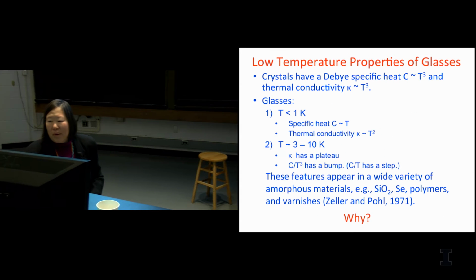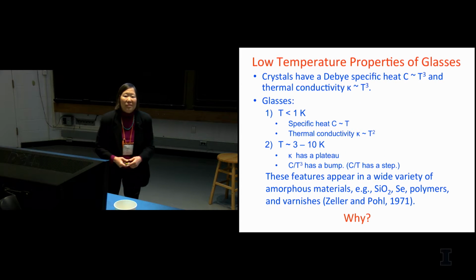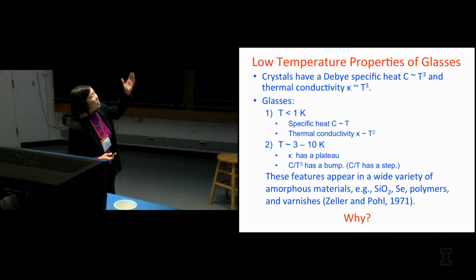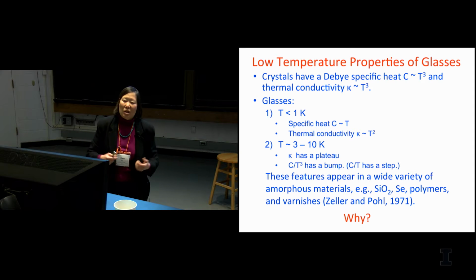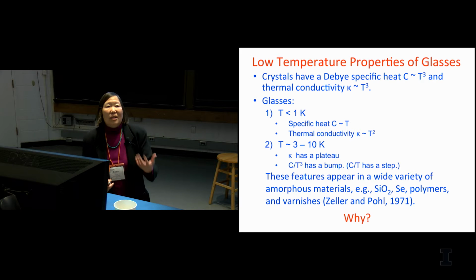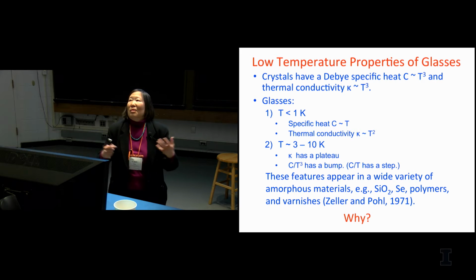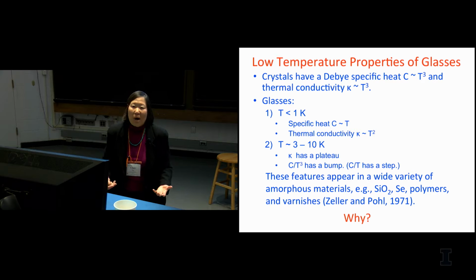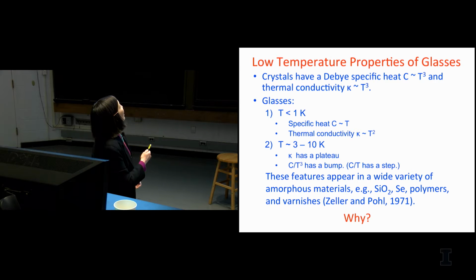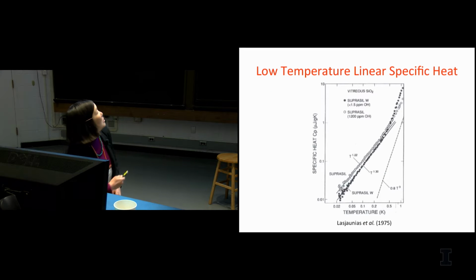So let me start by giving you a little bit of background on glasses. A crystal, of course, will give you a Debye specific heat that goes as T cubed. Thermal conductivity also goes as T cubed. If you take those same atoms, jumble them up, form a glass, you find very different thermal properties, in particular a linear specific heat. As we've heard about, this is specific heat versus temperature in a log-log plot. And actually, you get something superlinear, T to the 1.22, T to the 1.30.